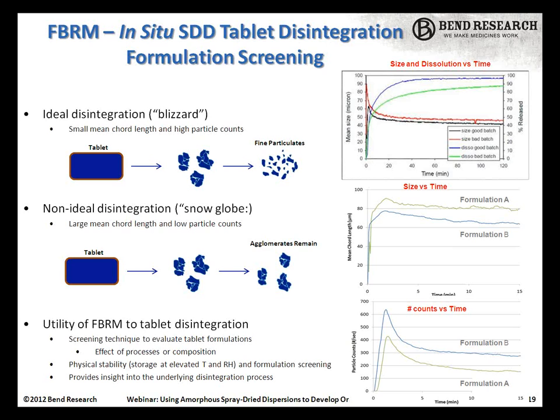And on this slide on the upper right-hand corner, what you'll see would be when we do compare the dissolution, the large particle size would give us lower dissolution, and that would be manifested by larger particles. On the middle screen there, the green curve would be larger particles. And then on the bottom, actually the number of counts is also lower for the slower formulation.